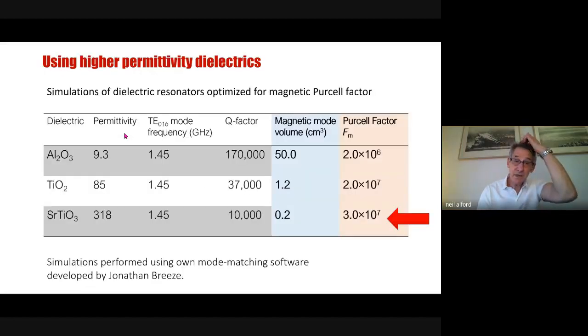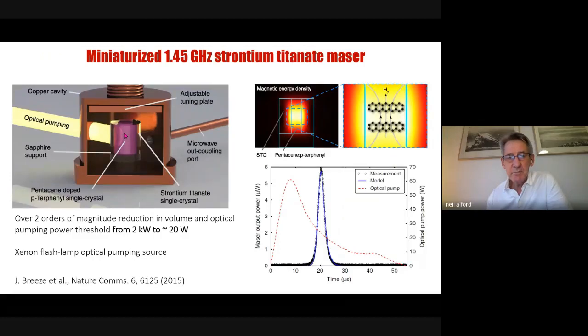And we were able to do that using strontium titanate. And you can see that the Q factor of strontium titanate is only 10,000 compared with 170,000 for alumina, but the magnetic mode volume is very small and the Purcell factor is very high. And the Purcell factor is the critical metric that we require in order to see how we can make this threshold for masing. And so here is the miniaturized strontium titanate maser.